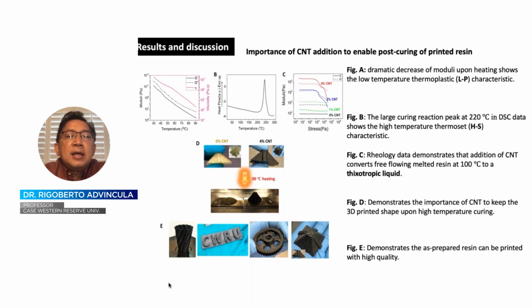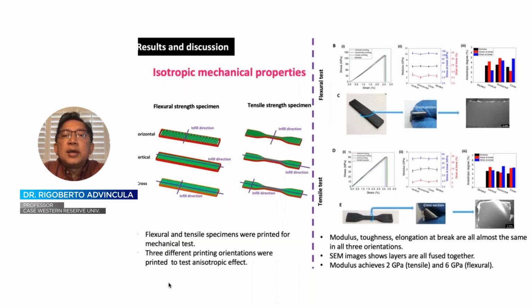E. Now, the initial printing with the presence of the carbon nanotube has to be heated at 90 degrees C. And the reason for that is to stabilize the object after you 3D print it, but at the same time, enable it to be completely converted to polybenzoxazine by heating it up to 200 degrees Celsius. In this case, since we did not load it with a very high amount of benzoxazine, we only need heating at 90 degrees Celsius in order to preserve the shape of the material. So another consequence of this is, since this is actually a thermoset that we 3D printed, these are isotropically oriented properties. In other words, independent of the direction of printing, we get the same properties in terms of the tensile strength, modulus, and toughness. It's because it's a thermoset material.